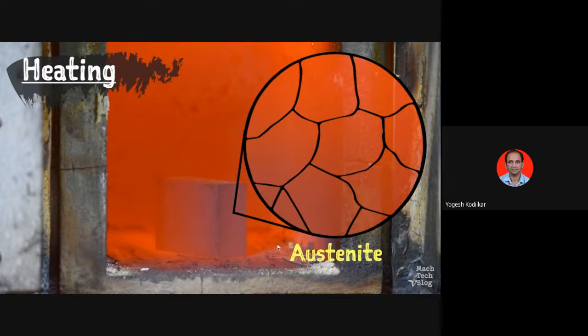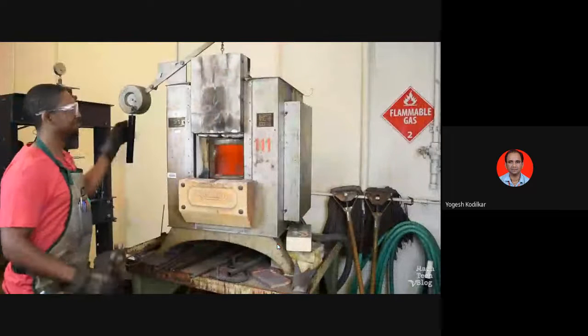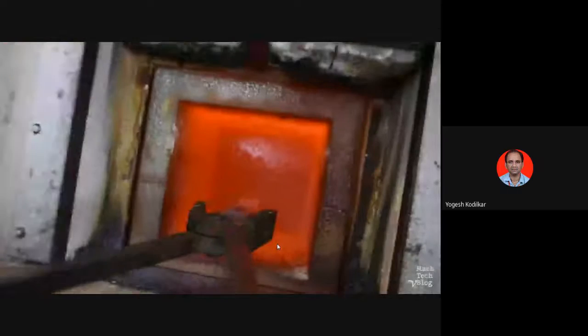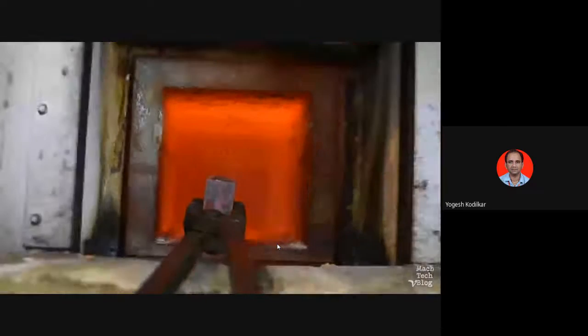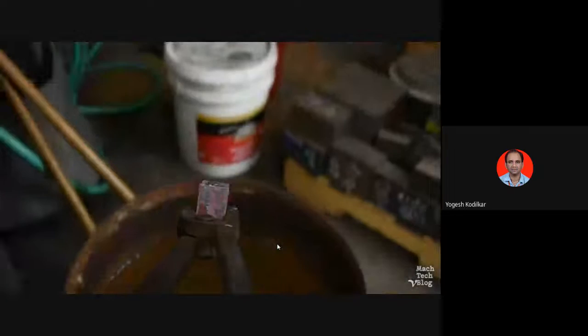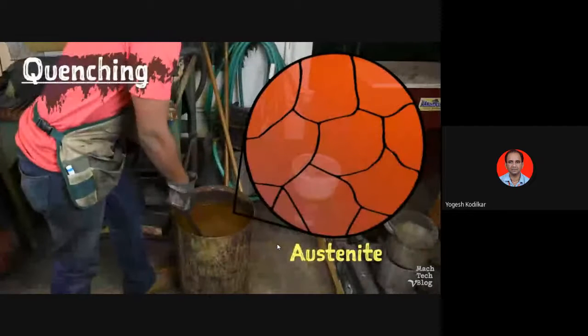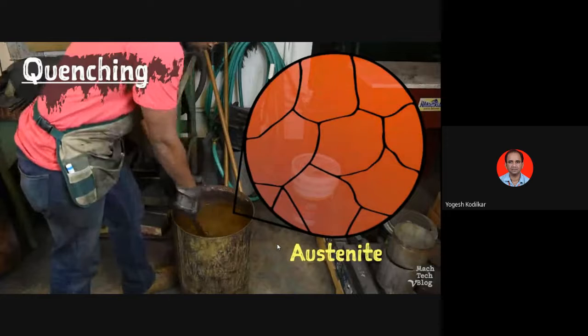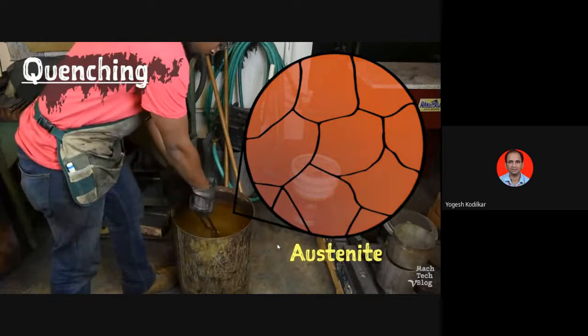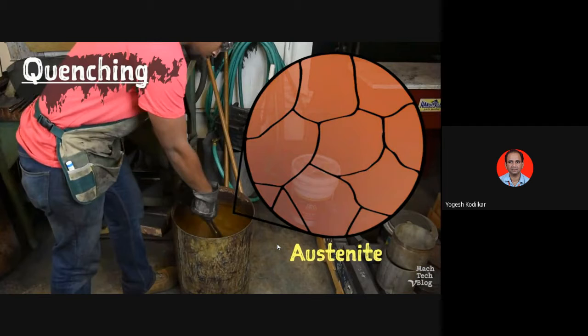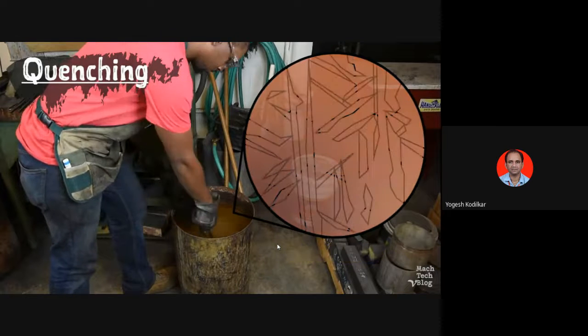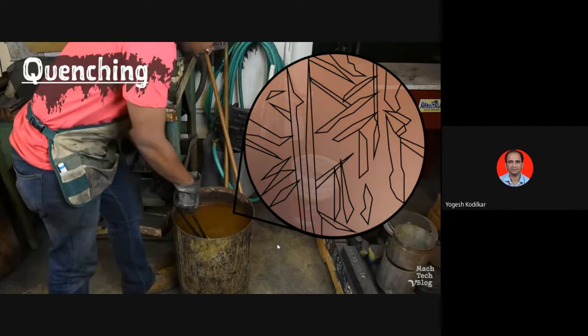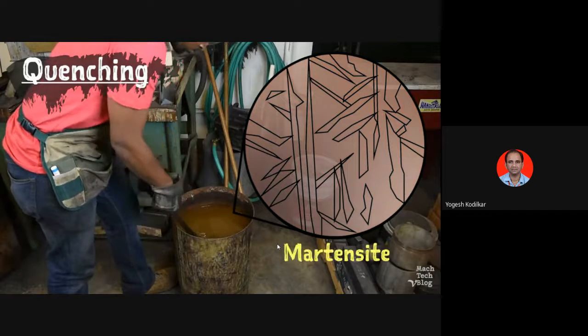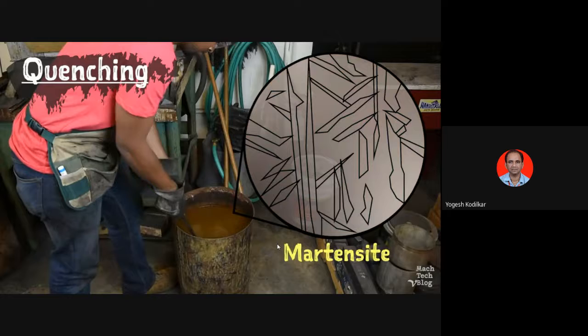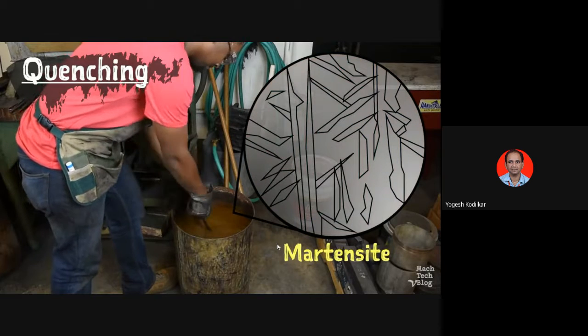Once all of the pearlite is dissolved, it's time to quench. Pull the parts out with a set of tongs. Quickly plunge them into a container of water and agitate the parts in a figure-8 motion until they're cool to the touch. Because we're cooling the steel so rapidly, the austenite won't have enough time to separate back out into iron and iron carbide. The resulting steel microstructure, called martensite, is composed of needle-like shards of iron supersaturated with carbon.